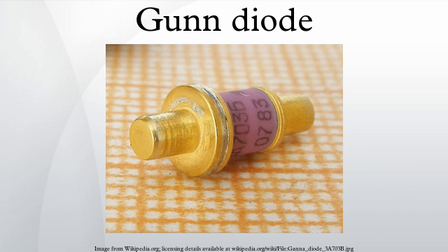How it works: the electronic band structure of some semiconductor materials, including gallium arsenide, have another energy band or subband in addition to the valence and conduction bands which are usually used in semiconductor devices. This third band is at a higher energy than the normal conduction band and is empty until energy is supplied to promote electrons to it. The energy stems from the kinetic energy of ballistic electrons. That is, electrons in the conduction band but moving with sufficient kinetic energy can reach the third band.